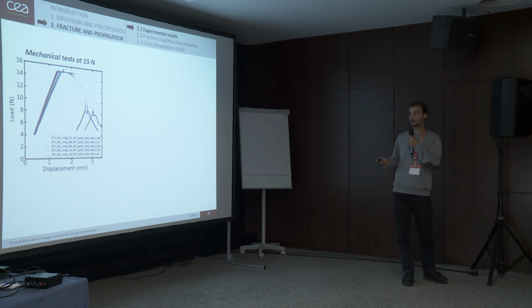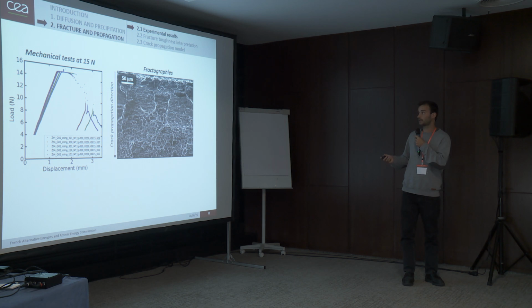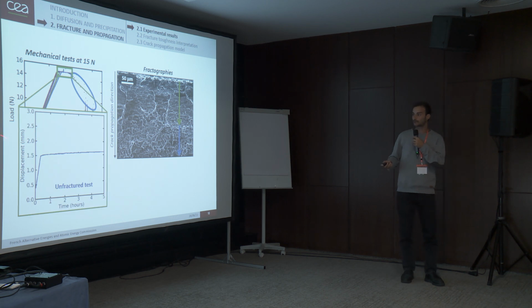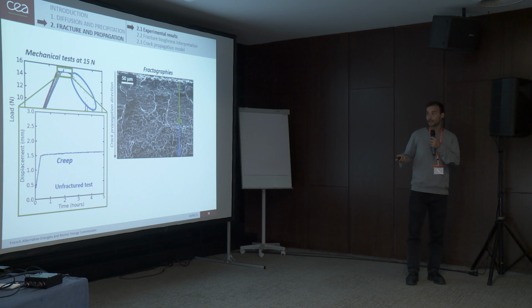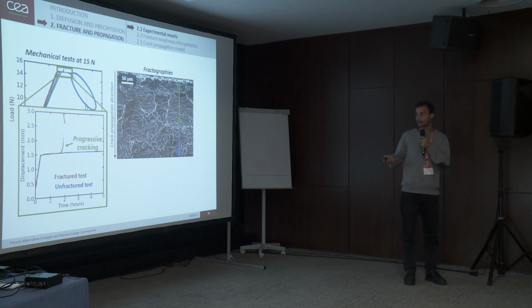So as I said before, 4 tests out of 5 led to fracture. And if you look at the fracture surfaces, we can see that there are 2 fracture modes, the green arrow and the blue one. And if you look at the displacement versus time curve for the unfractured test, you can see there is a small increase of displacement that corresponds to creep. And if you compare with a fracture test, you can see that the displacement increases quicker.